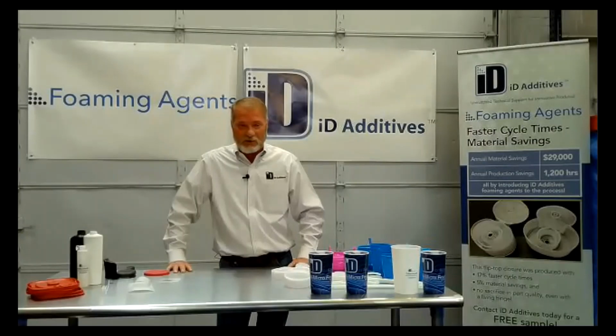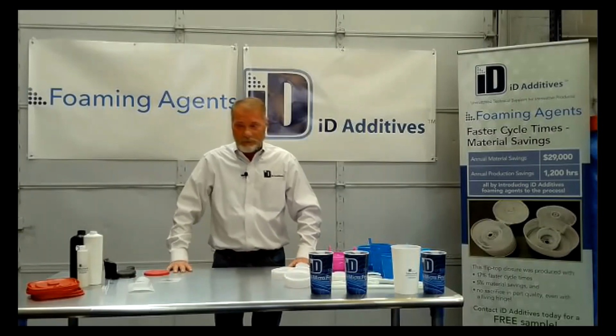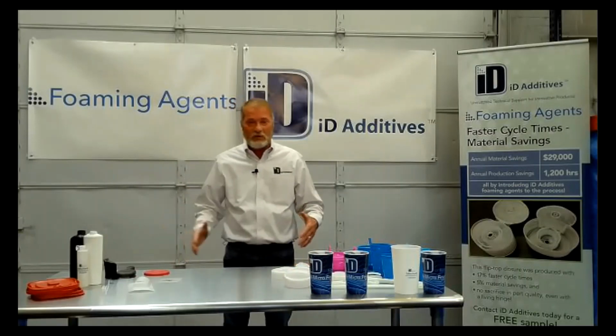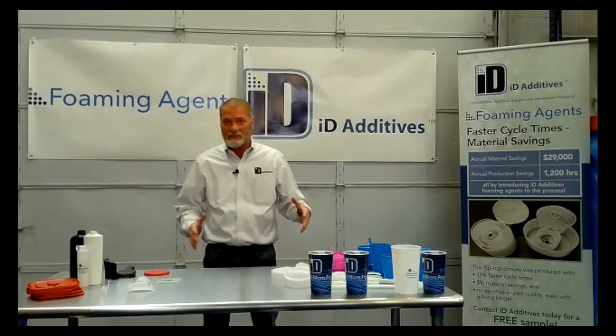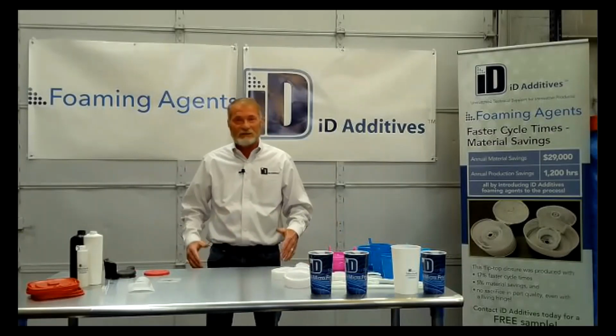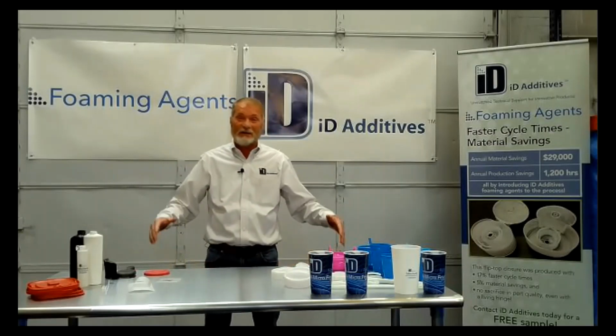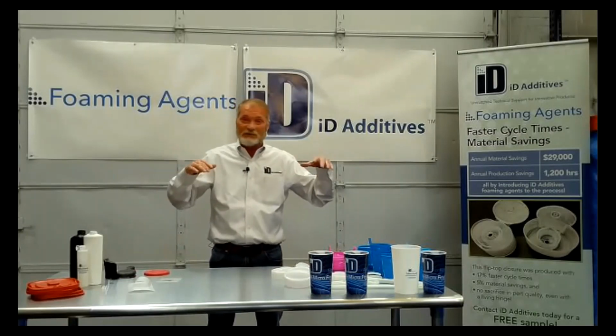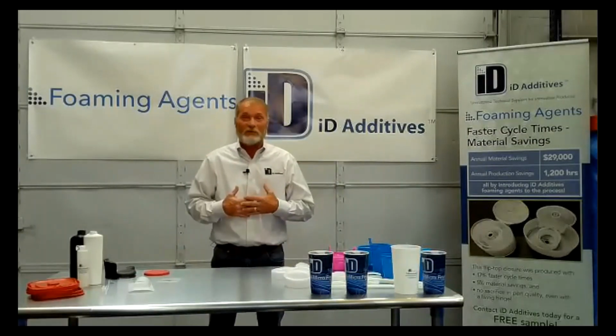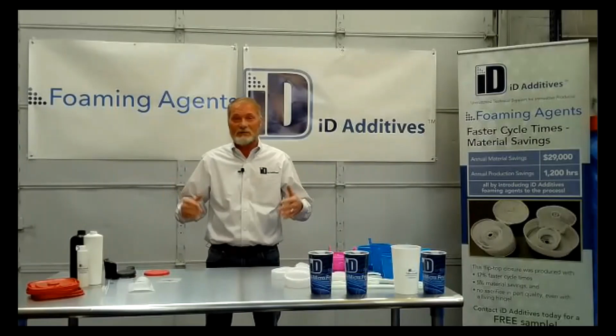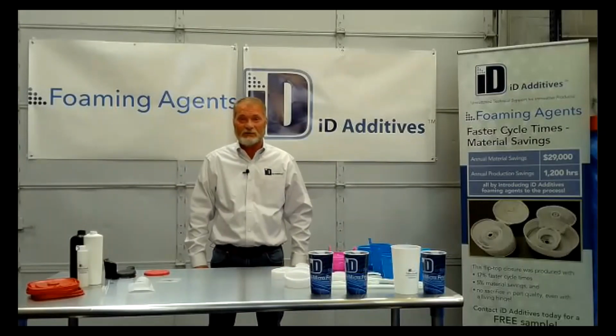I've done tests where all I did was adjust the residence time, and I took an added pound out of the part. So that residence time, keeping it moving, no delay, no sitting there baking, makes a huge difference in your process. Even if you're running your temperatures a little warmer than what I would prefer, that residence time is going to make a big difference in what you're doing.